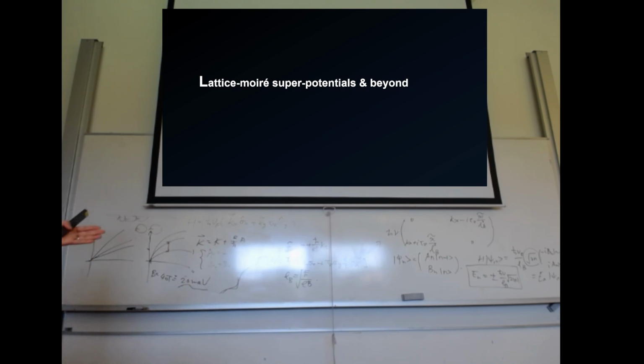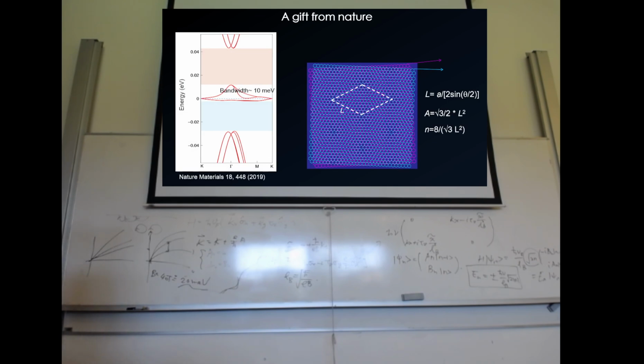The moiré system was mostly realized by twisting the lattice of two-dimensional materials. There's another system people have been working really hard on theoretically: two layers of graphene, a semimetal with Dirac fermions. There are no strong interactions, no superconductivity, no magnetism, just a single-particle picture from two sheets. You just put them together and align them. If you align them correctly, at some magic angles, the Dirac point will be gapped out and the central band will become a flat band, with a bandwidth of only about ten milli-electron volts.